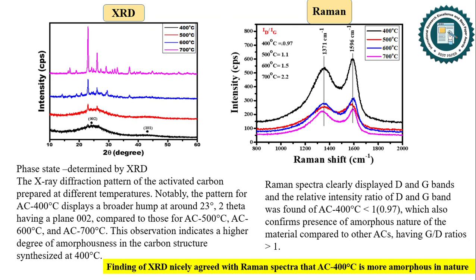First, I'll start with XRD. So the phase state of activated carbons was determined by XRD. The XRD diffraction pattern of the activated carbons prepared at different temperatures are shown over here. Notably, the pattern for AC 400 degrees centigrade displays a broader hump at around 23 degrees 2 theta, having a plane 002, compared to those of 500 degrees centigrade, AC 600, and AC 700 degrees centigrade. This observation indicates a higher degree of amorphousness in the carbon structure synthesized at 400 degrees centigrade.